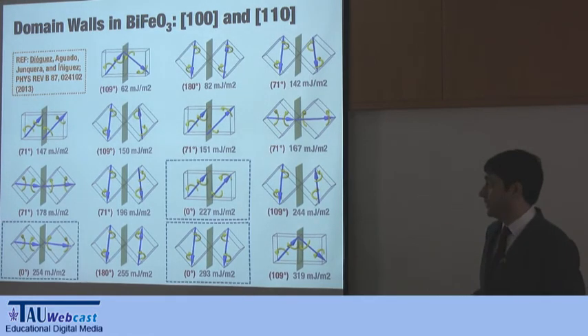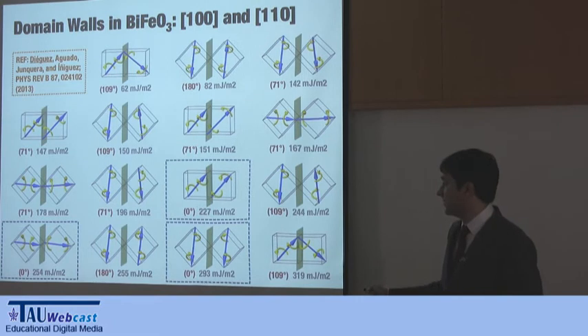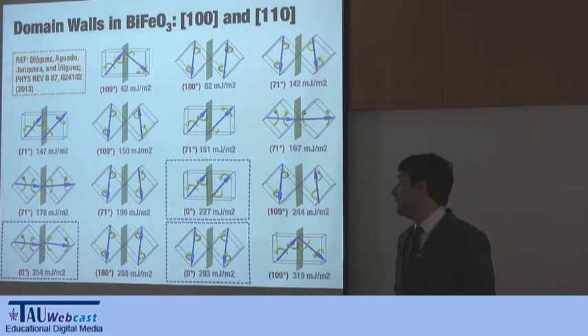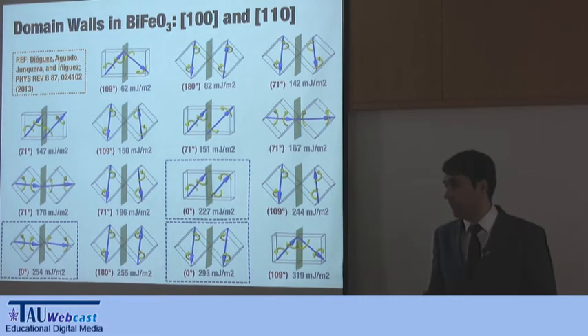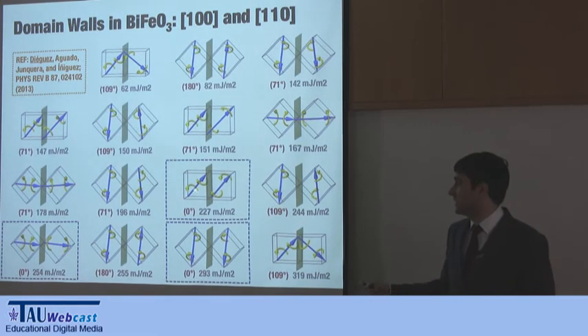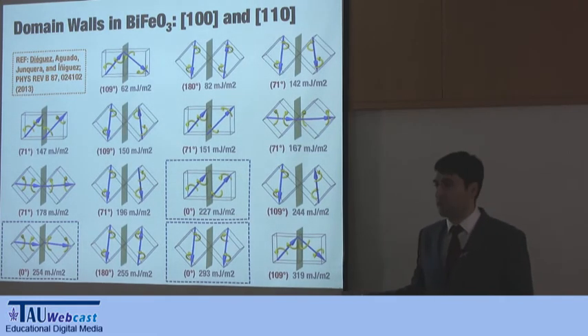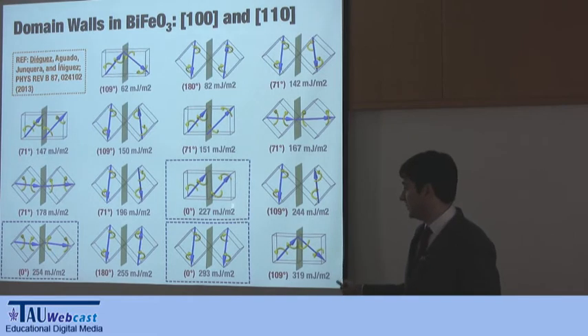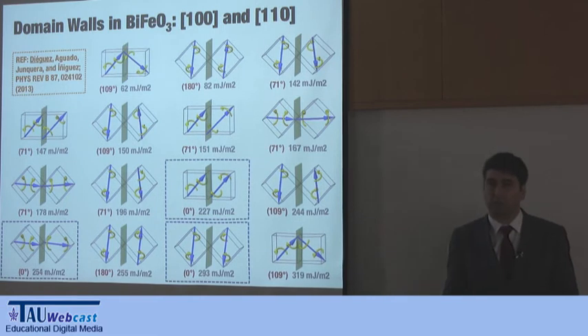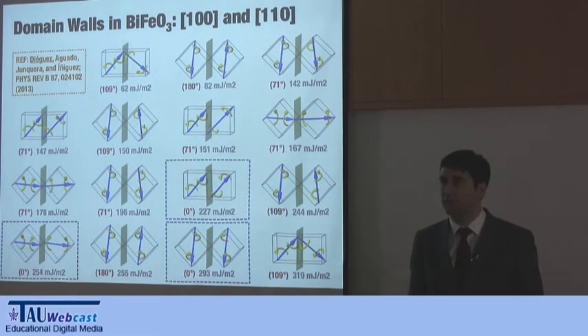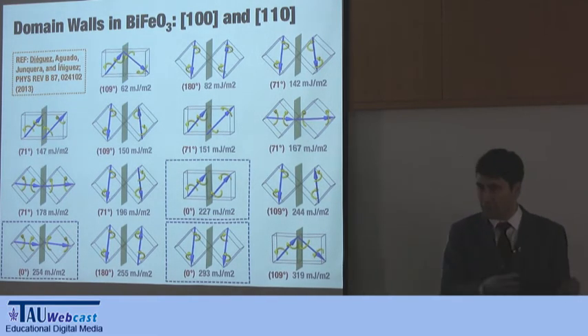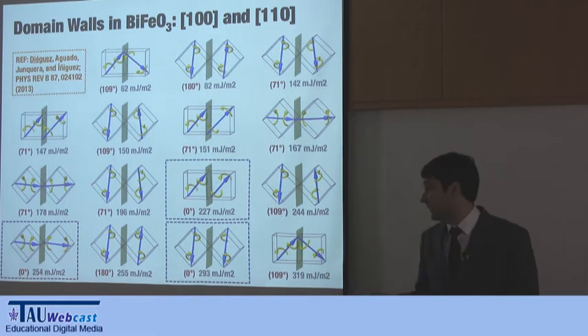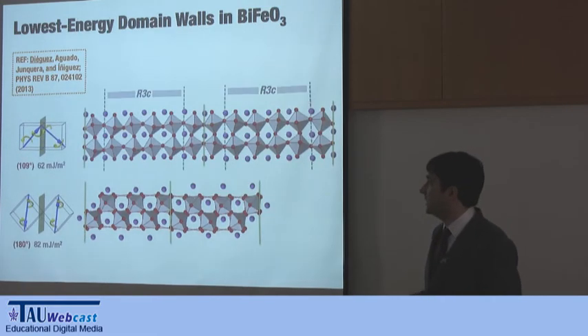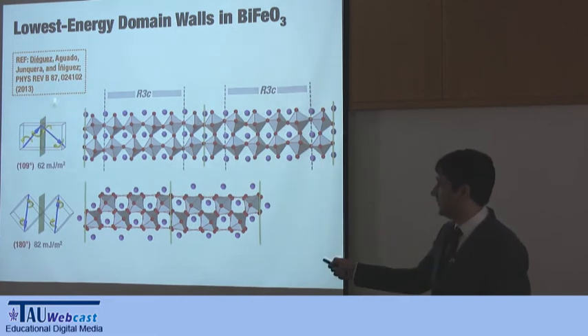And one interesting thing is already that contrary to ferroelectrics where there is no octahedral rotation, the ones that keep the ferroelectric polarization in the same direction are very high in energy if the octahedral rotation don't match. So what is costing energy is not the polarization change, which is what happens in most ferroelectrics, but the octahedral rotation. You can see it here that if you have, this is the real cell we used for the simulations.